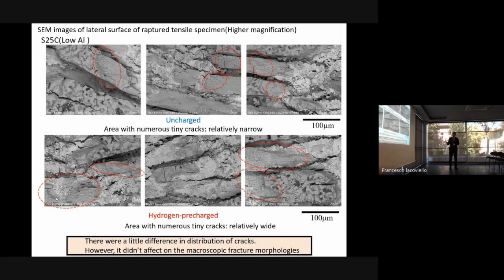Next, these are higher magnified pictures, uncharged and hydrogen charged. The red circle shows, maybe you can't easily see, tiny, very small cracks that initiated. Inside the red circle, they are in a relatively narrow space in the uncharged one. In contrast, in the hydrogen precharged one, tiny cracks are relatively widely distributed. There was a little difference in the distribution of cracks, but it didn't affect the macroscopic fracture morphology.